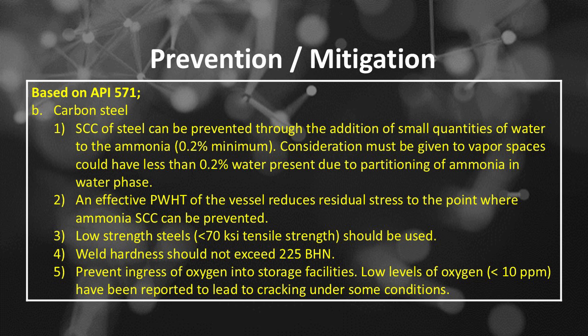Number B, carbon steel. Number 1, SCC of steel can be prevented through the addition of small quantities of water to the ammonia, 0.2% minimum. Consideration must be given to vapor spaces, which could have less than 0.2% water present due to partitioning of ammonia in the water phase. Number 2, an effective PWHT of the vessel reduces residual stress to the point where ammonia SCC can be prevented. Number 3, low-strength steels, less than 70 ksi tensile strength, should be used. Number 4, weld hardness should not exceed 225 BHN.